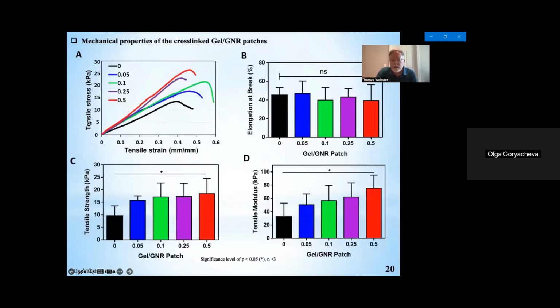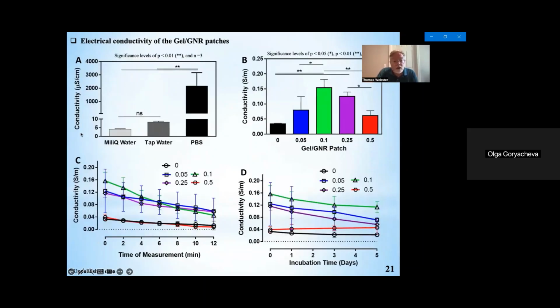Mechanical properties are right where they need to be. Looking at tensile strength as an example, elongation at break, tensile modulus, the gelatin graphene nanoribbons have mechanical properties that are close to that of heart tissue itself. Electrical conductivity is also pretty similar to natural heart itself. Here's some conductivity measurements in various media, where the conductivity is in Siemens per meter. You can see that we get an increased conductivity. And then interestingly, when we add more past 0.1 weight percent, we start going down. This is because some of those nanoribbons agglomerate into larger structures. So we're losing some of the electrical conductivity, but nonetheless, they're still conductive enough for heart tissue applications.